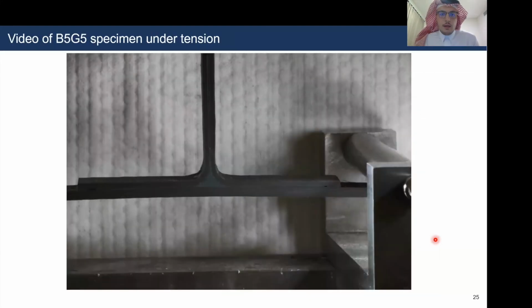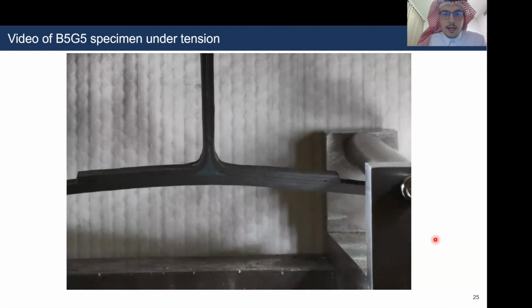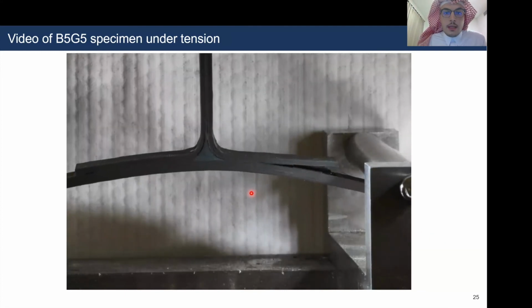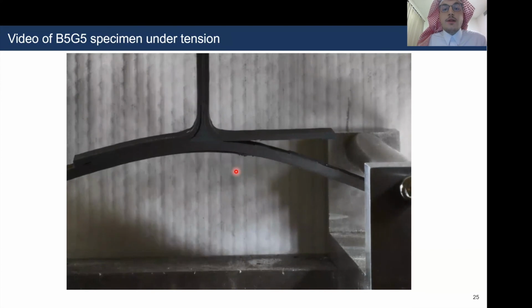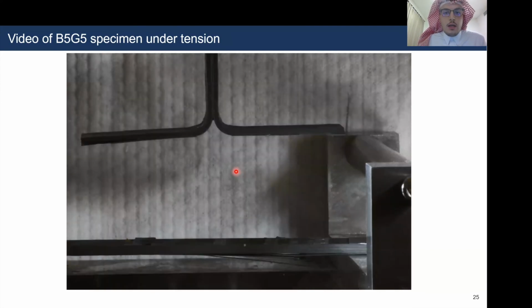So when the adhesive ligaments happened, they resulted in enhanced toughness, and that indicated a safer T-joint. As compared to P-ply, if I was to show a video of a P-ply failing, then the failure would not even be recorded. The cracks would just propagate really quickly, and sudden or catastrophic failure would happen.